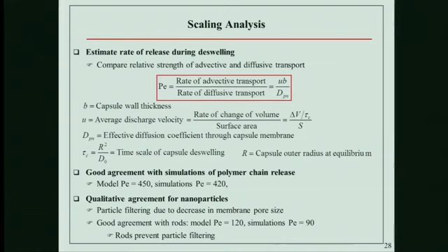And if we multiply it by the concentration inside, that gives us a good estimate of how many particles we will release, right? And then if we compare it with the results for chains, this is what the model predicts, and that's what we see in the simulations for 450 versus 420, very close agreement. So indeed, that's what happens. This is the release by this hydrodynamic process.